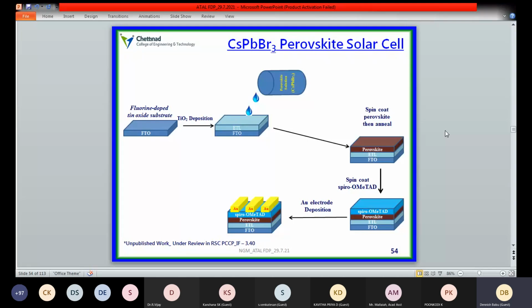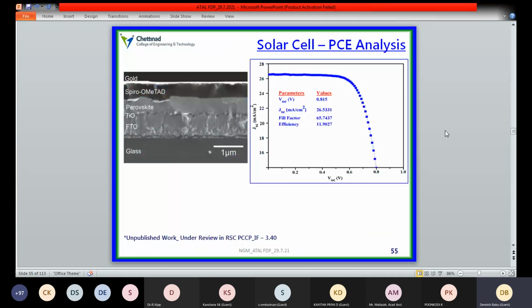And above that electron transporting layer, we have deposited the perovskite solution, especially cesium lead bromide solutions, with the help of a simple spin coating method. And above that perovskite layer, we have coated a spiro-OMeTAD layer, the hole transporting layer, again with the help of spin coating. After that, we have deposited gold as a contact layer for the perovskite system with the help of electron beam evaporation. So this is the typical cross-sectional image of the prepared perovskite system. FTO, TiO2, perovskite and spiro-OMeTAD layers, and above that the contact layer, are easily visible in this cross-sectional image. So I'm very happy to introduce the first result of this cesium lead bromide based perovskite system. We have achieved almost 11.9% efficiency in the cesium lead bromide based systems.